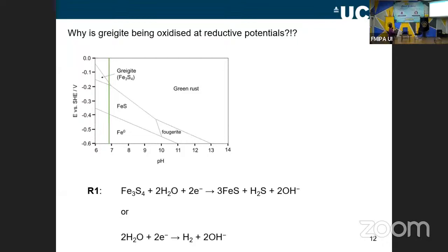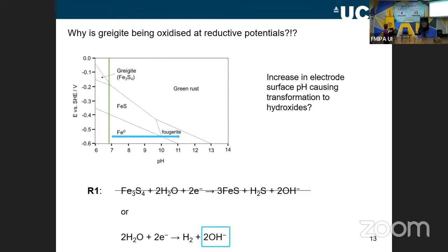Especially when you look at this diagram, which suggests something else should happen. And that reaction that we initially thought would happen would be iron 3 went to iron 2 and then maybe iron 0. But we see no evidence for that reaction happening. What we do think is happening potentially is that the current is due to this reaction instead.